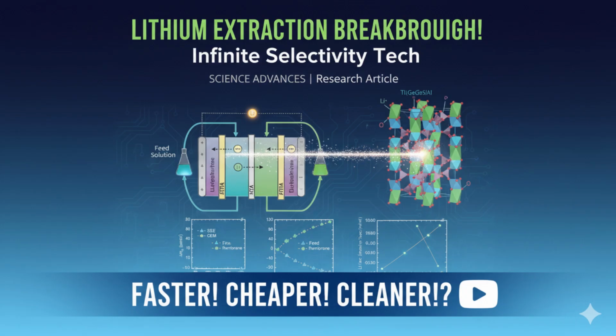Basically, it becomes a bare lithium ion. And then, driven by an electric field you apply across the membrane, it hops. It physically jumps from one specific vacant site to another within the solid crystal lattice of the Nasicon. Like moving through a series of atomic-scale docking stations inside the crystal. That's a great way to put it. It's solid-state diffusion. And because it's happening inside this tightly packed, precisely structured crystal, the material can be incredibly picky about which ions can make that journey. It's like an atomic-scale sieve or, like you said earlier, maybe a very exclusive nightclub.